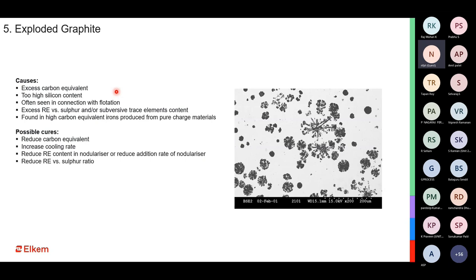One of the elements which does support exploded and chunky graphites is rare earth. So when you have a high rare earth content, especially for the heavy section or a slow solidifying section, there is a strong tendency of exploded graphite happening.